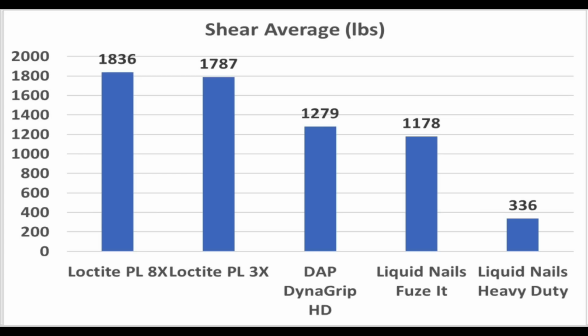The results of the shear strength test are very interesting, with Loctite 8X winning the first round with an amazing 1,836 pounds of shear strength on average. It would have likely won by an even larger margin over 3X, but 8X was stronger than the wood. PL3X, which was also stronger than the wood, did very well too at 1,787. DAP Dynagrip finished third at 1,279. Liquid Nails Fuse-It at 1,178. And I'm really surprised that Liquid Nails Heavy Duty didn't do a little bit better. Let's test the tensile strength of these products next.